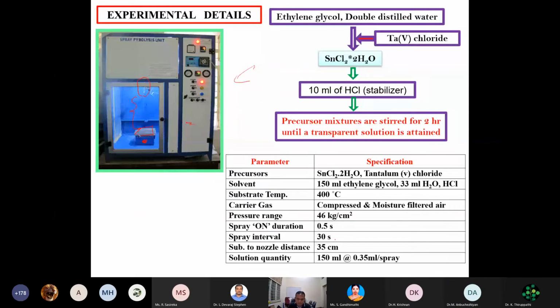So I will be spraying for 0.5 seconds. Just a moment only I will spray. That aerosol will come to the substrate and then that itself will cool my substrate nearly 75 to 100 degrees centigrade. So I have to wait for 30 seconds for the heater to supply heat and to regain the temperature. Then only I can maintain the temperature suitable for my decomposition. So these are the conditions.